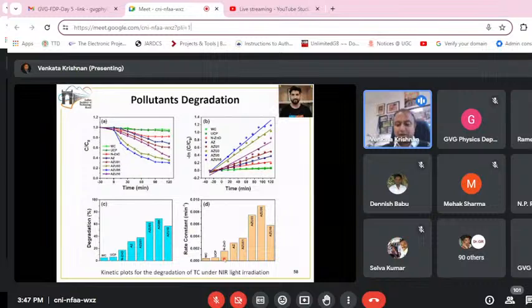First we did the experiment under NIR radiation, and we found one of the samples, AZU05, gives the best photocatalytic activity, which indicates that the photocatalytic activity is mainly because of the upconversion nanoparticle present in the system.